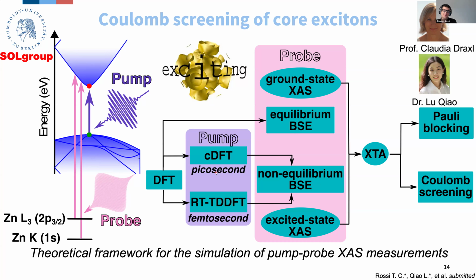So what you can do in principle to model this specific excited state is that you can manually promote carriers between the valence band and the conduction band. So you manually promote these carriers and you set them according to a Fermi-Dirac distribution. This is called constrained DFT, and it's one way to calculate the electronic structure of an excited state. So that's what Lu did to simulate the results of picosecond experiments.